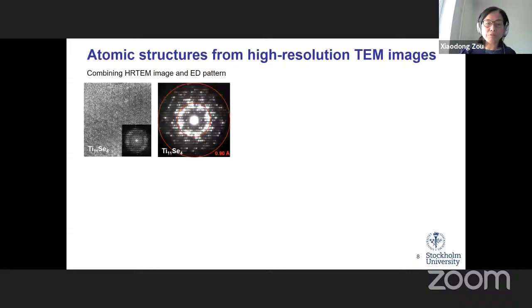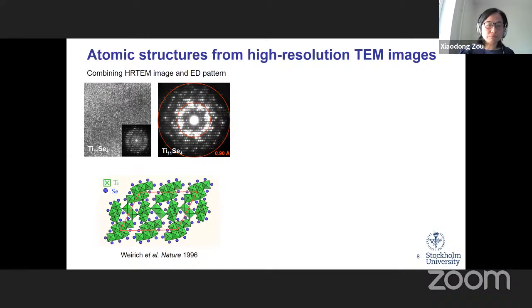When you have high resolution images, you can use only high resolution images or combine images and the electron diffraction. And we did that in the 90s already to show that it was possible to solve unknown structures using electron crystallography, as we call it. Images are usually very demanding. You need a very good microscope, and still you don't get very high resolution. Electron diffraction is easier, and you can easily get sub-angstrom resolution. Combining these two techniques is a very good approach.